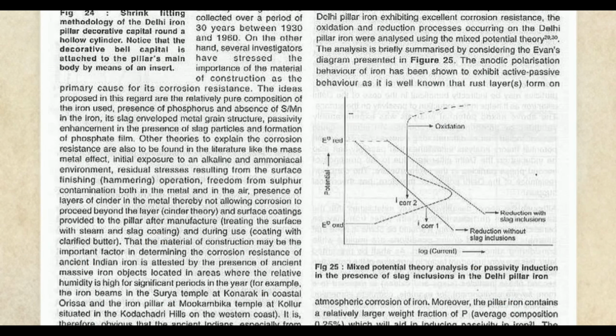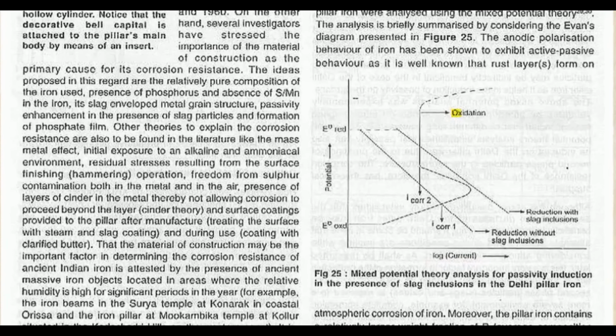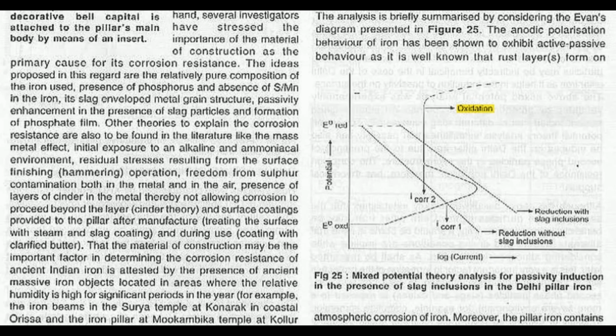This Evans diagram maps these competing reactions using mixed potential theory, plotting the log current on the x-axis against the electrical potential on the y-axis. The upward curve represents the anodic polarization behavior, the oxidation of the iron matrix. The dashed line on the left shows the theoretical initial cathodic activation, how the iron would behave if there were no slag inclusions present. But the fayalitic slag acts as a massive sink for electrons. This increases the exchange current demand, shifting the cathodic activation line to the right.